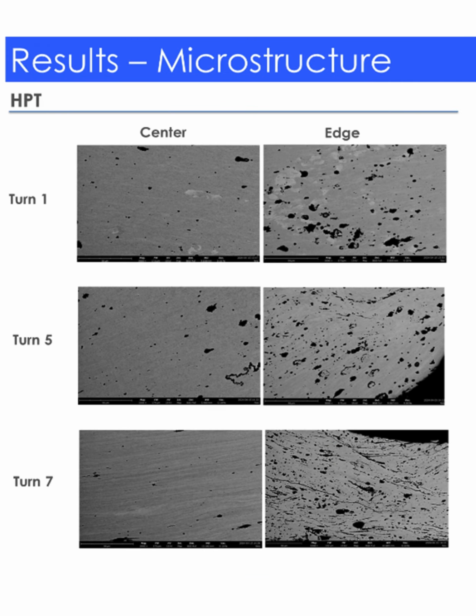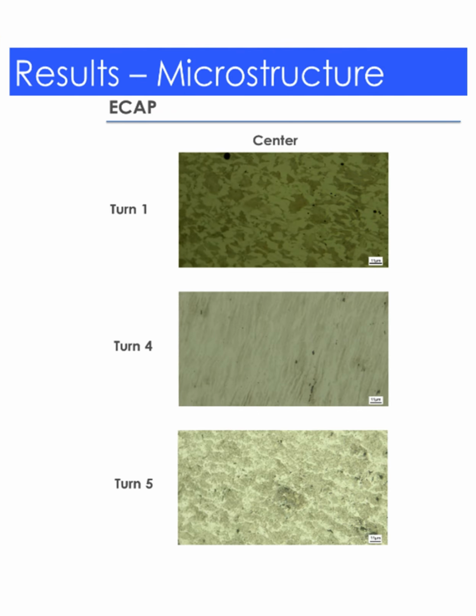In the microscopy results, we observed the influence of deformation on the steel's phases. For HPT, the pearlite deformed in the same direction as the applied rotational force, and cracks appeared more frequently as the number of rotations increased. In the case of ECAP, as the number of passes increased, there was a successive subdivision of dislocation walls due to the activation of multiple slip systems, leading to a higher level of deformation.